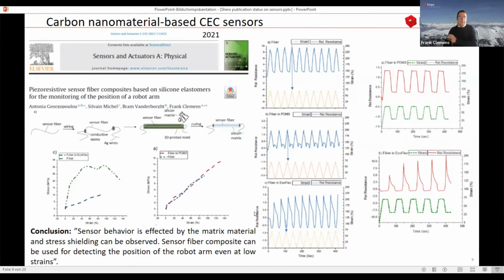And then we did some mechanical analysis, and we tried to do some composite analysis, and we could see that when we have a lower stiffness of the matrix, we cannot calculate anymore the strain-stress behavior of a fiber. That means the fiber is somehow decoupled from the matrix, or in other words, we have a strain shielding of the matrix, and that means that the fiber will not see the strain which we apply to the matrix.